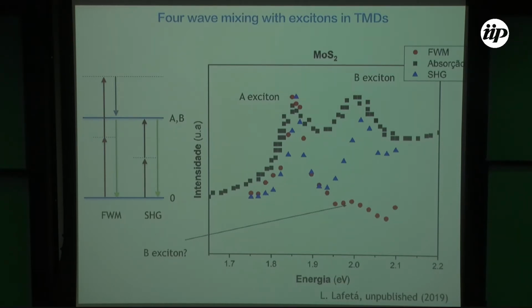So here, I'm not going to show it. This is some ongoing work, but we have measured other different transition metal dichalcogenides, and the trend is very similar. Okay, we don't have the four-wave mixing emission from the B exciton. Okay, so this is a result that we don't understand up to now. We would expect that the four-wave mixing, since it's a third-order nonlinear process, the selection rules should be very similar to the linear optical part, okay, but we are still trying to understand the reason for that, okay.